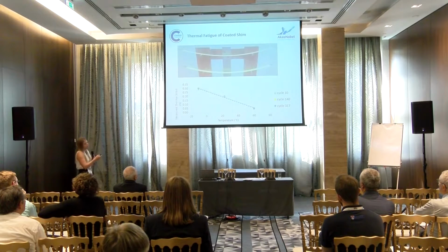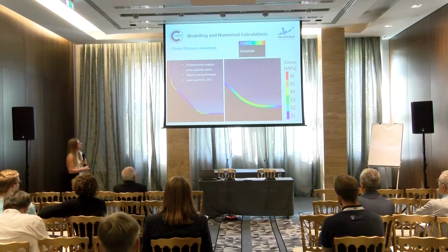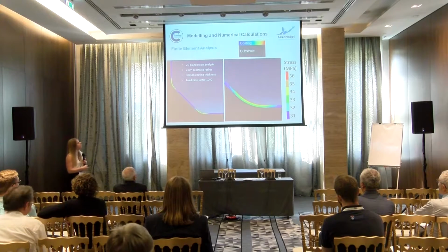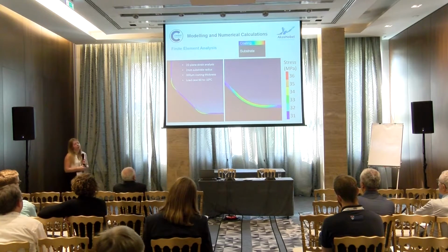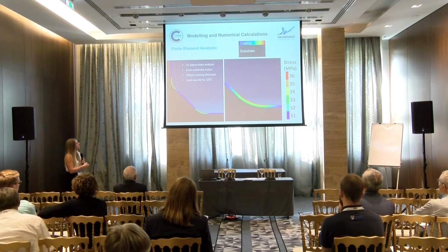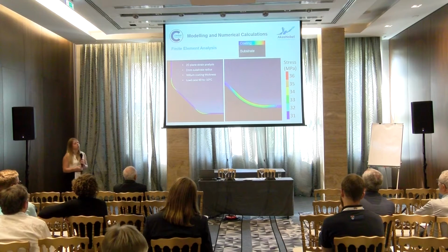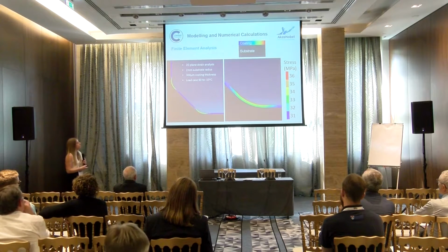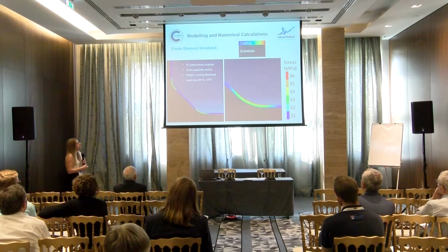Of course, this just tells us what strain levels you might see on a flat surface of a coating applied to a steel substrate. So in order to understand what local strains might develop within the profile of the T-section, finite element modeling was employed. So this is a 2D plane strain analysis with a 2 millimeter substrate radius and a 300 micron coating applied to the substrate. The coating properties that were identified earlier were input into the model, and a thermal load from 60 to minus 10 was applied with assumed zero strain at 60.